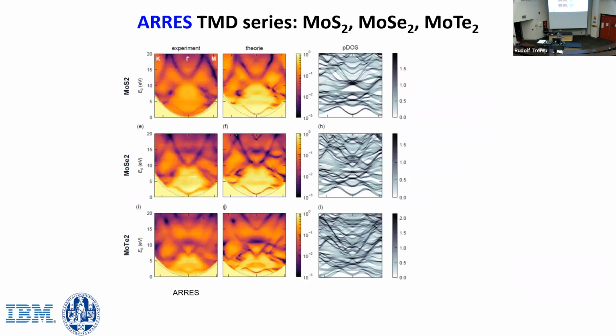And here's a similar series for different metal dichalcogenides. For instance, here you see a very pronounced state inside the band gap in theory, which we also find in the experiment. And then you see these strong parabolic bands up here, both in theory and experiment. You can see them in the spaghetti plot here, these strong parabolic bands. You have direct access to the unoccupied bands in the material. This is interesting because nobody's done this before. There's like tens of thousands of papers on angle resolved photoemission, but nobody's been able to look at these unoccupied states before. And here for the first time, we really get a very detailed look at them.